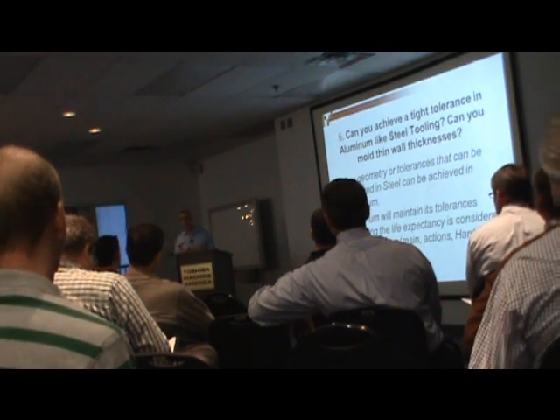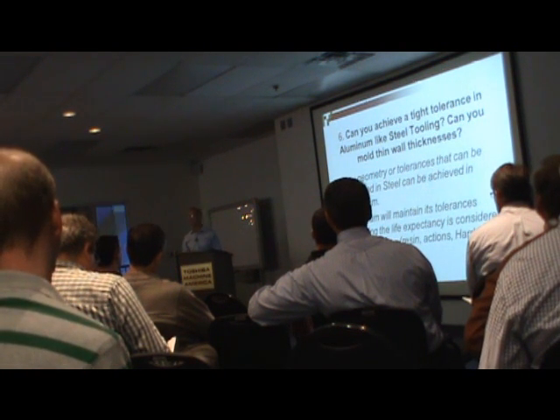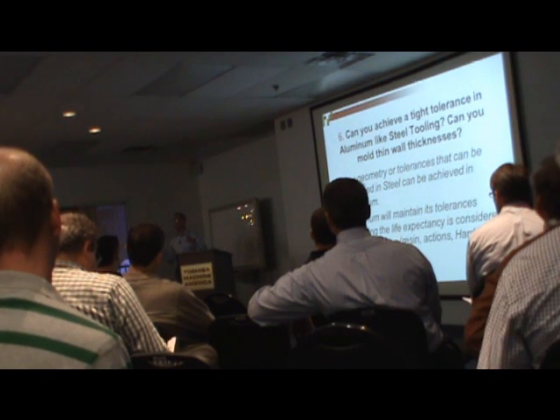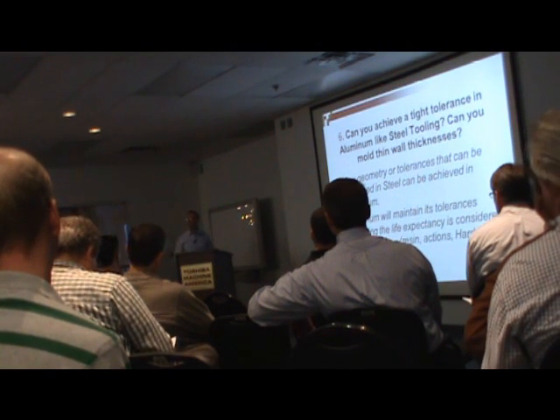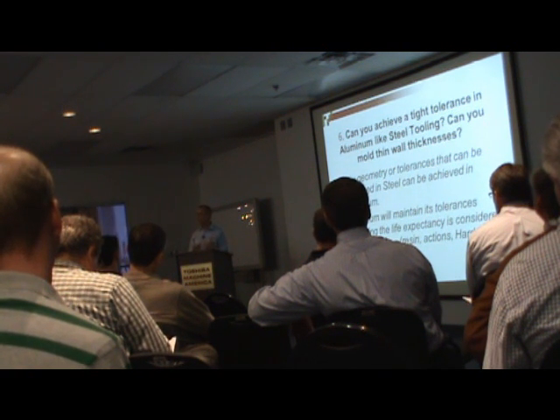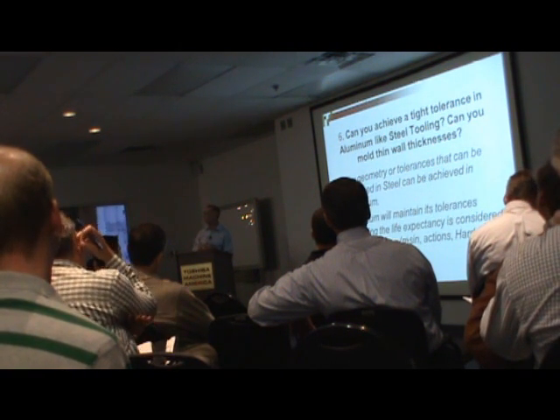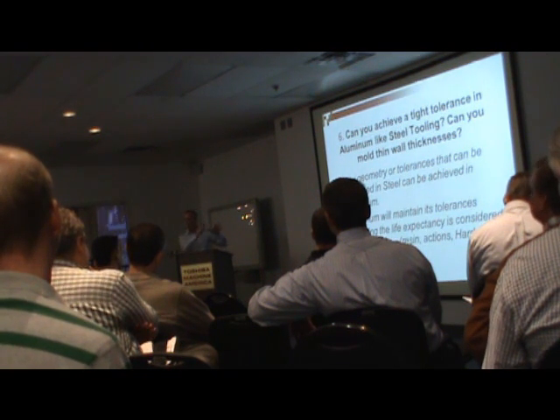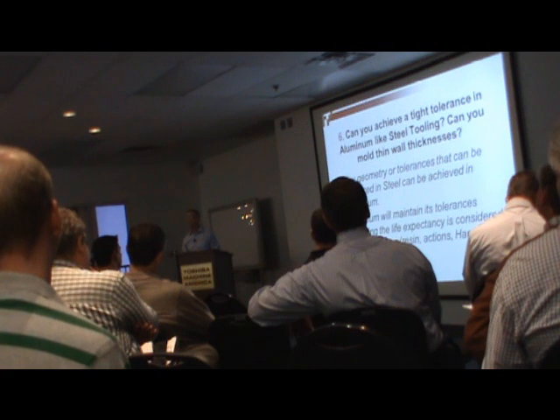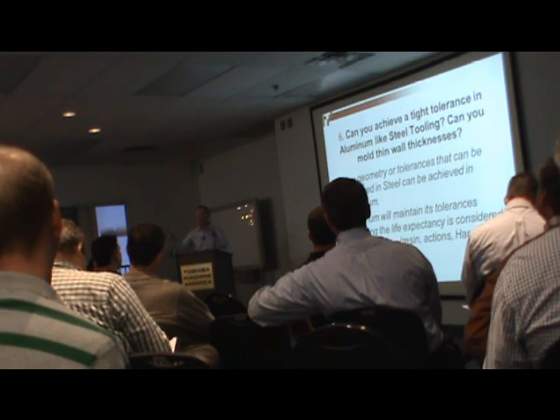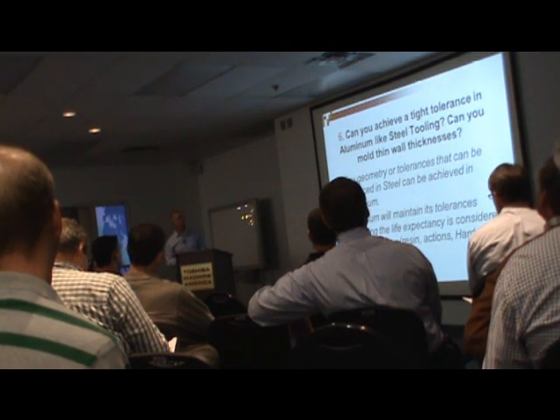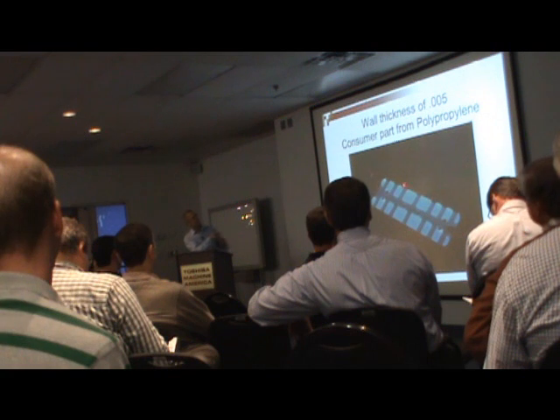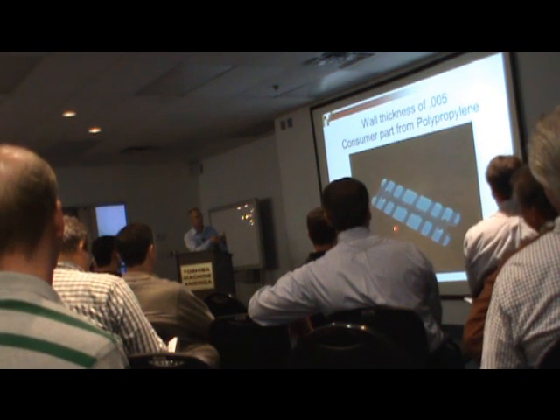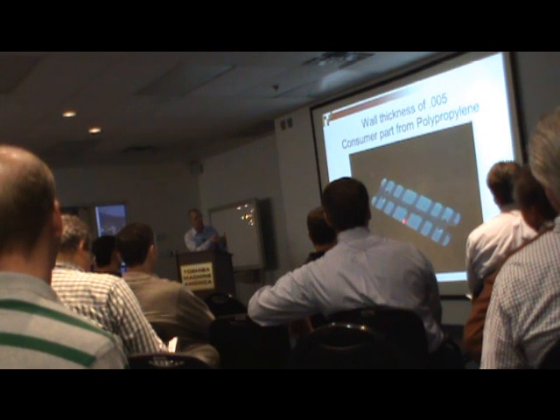In fact, there are studies, not done by us, studies done by some very reputable people out there, and I know that Alcoa was involved with this, showing side-by-side comparisons between aluminum and P20 steel, that in some critical dimensional areas they can hold the aluminum much tighter temperature-wise, which equates into a better quality part than you can in steel, because the steel will vary, either in injection time or the actual mold temperature. So it's not just coming from us. These are various people doing these studies to prove this out. The reason I have this part, the wall thicknesses, we do thin wall in aluminum. It's down to 5 thousandths. I think it's up to 30 thousandths in this area here.